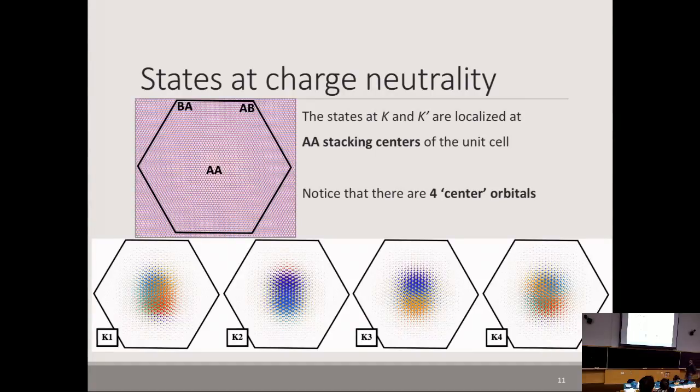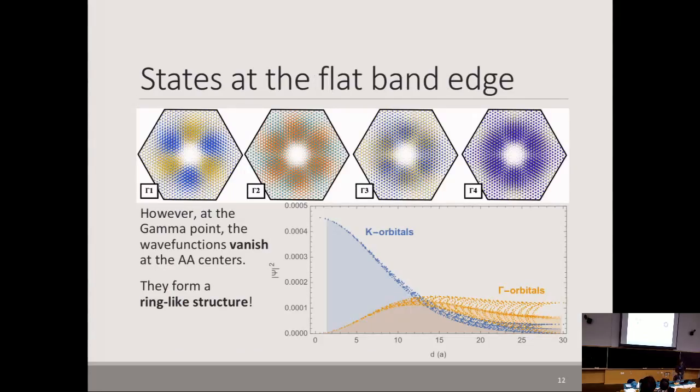Then how these look at the gamma point, they are not exactly orthogonal. However, what we can do is take these, now I have 8 orbitals, I can just Gram-Schmidt orthogonalize them, in which case I have 8 orthogonal wave functions within the unit cell, and then I can just project the Hamiltonian, like this 11,000-band Hamiltonian, onto those 8 bands, and I get this thing that I had in the next slide.